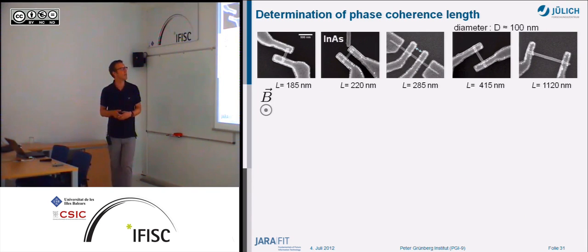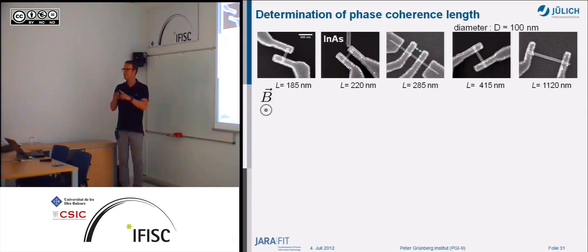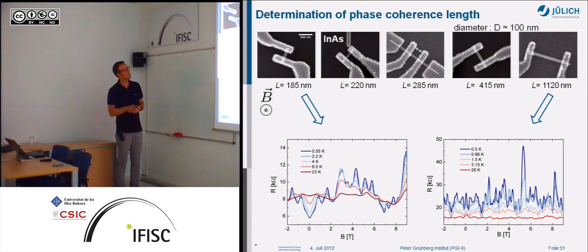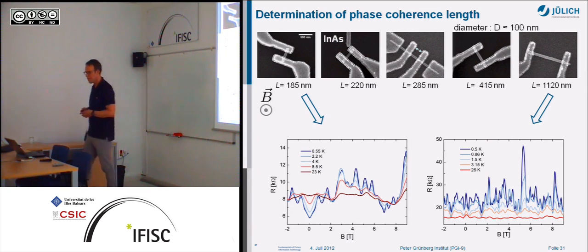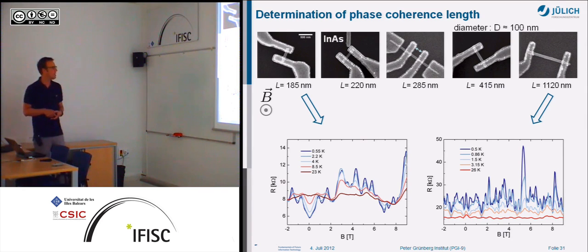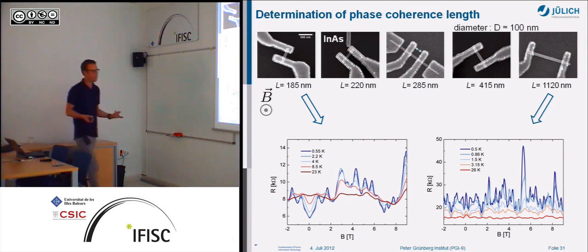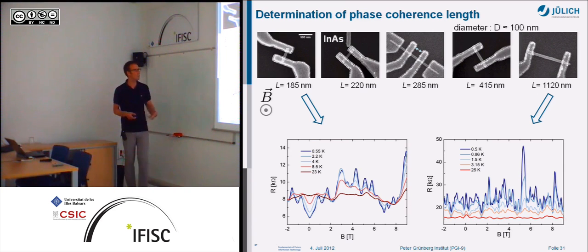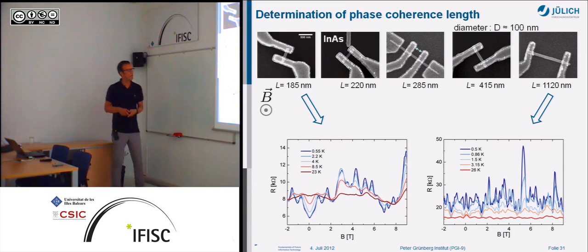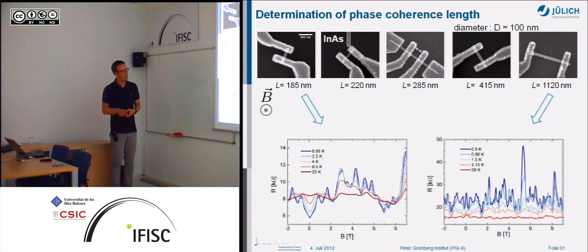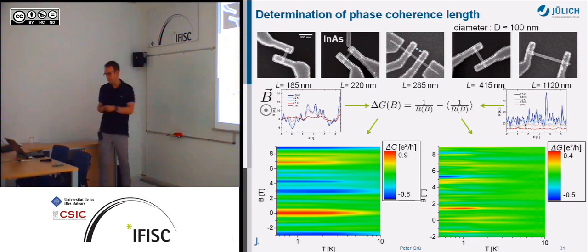So we have a set of nanowires with different contact separation. Here we have a short contact separation. It's getting longer and longer. What you observe here is that we first of all see these conductance fluctuations. They are reproducible. If you repeat the measurement here, you see that the fluctuation pattern is the same. Here the amplitude is decreasing if you increase the temperature, but the pattern is the same. What you see here, if the nanowire is longer, you have more fluctuations. The temperature dependence is also different.